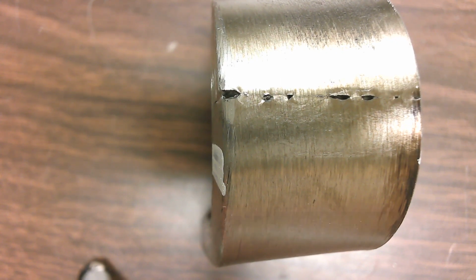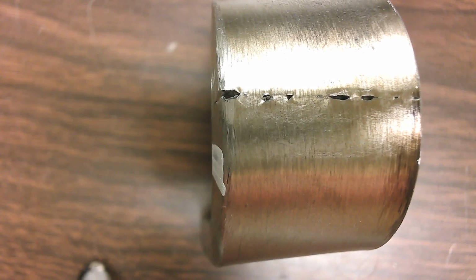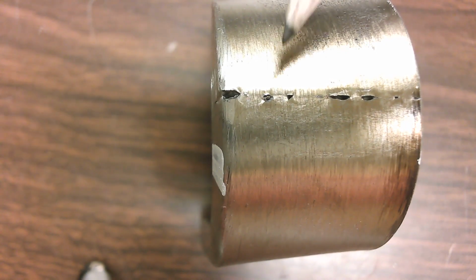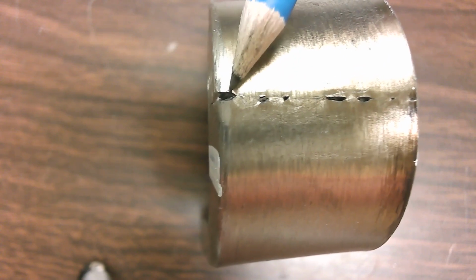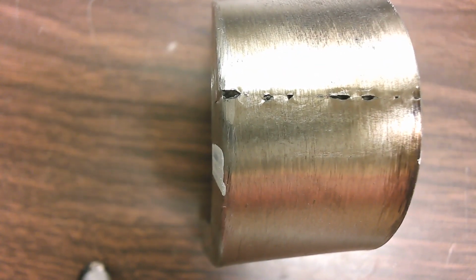I still also do levels for grading. We're on a 4-point standards-based grading. So in order to pass a bend test with a 4, obviously it needs to pass for AWS standards. Then I go into levels of, well, how did it not pass? Is it just barely not passing? Are we just adding up a total of small discontinuities and it just didn't quite pass? Then it's sitting at about a level 3, depending on a few other scenarios. Did it break completely in half and have 2 separate pieces? Well, you're going to be sitting at a 1 for a grade there. Did it hold together, but it cracked almost all the way through, or lots of discontinuities, big slag inclusions, that kind of stuff? Then you might be at a 2, but it has to hold together in order to get a 2. So that's kind of my scale. That's what I came up with.